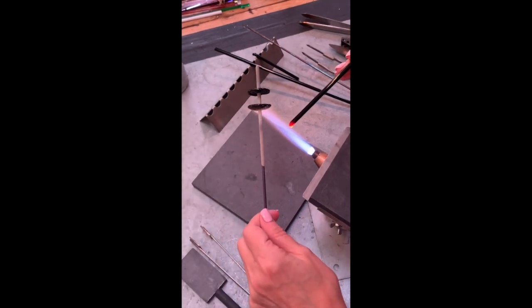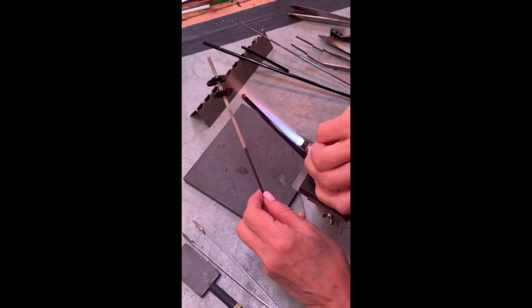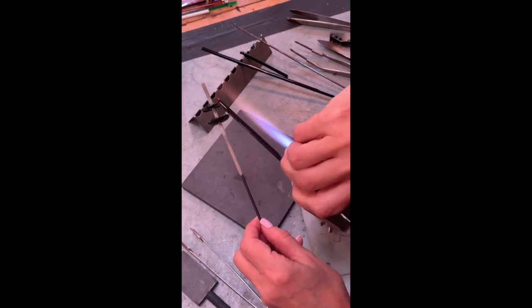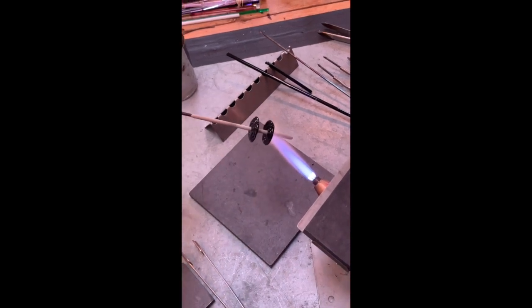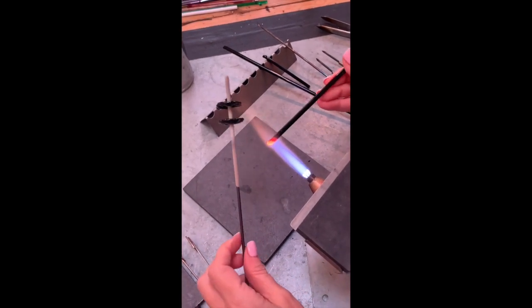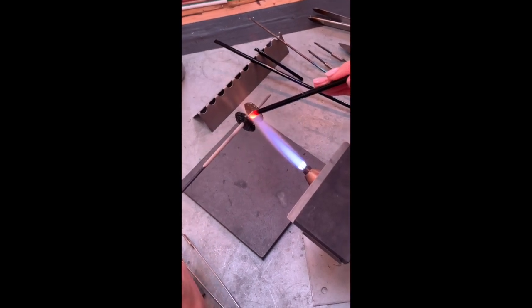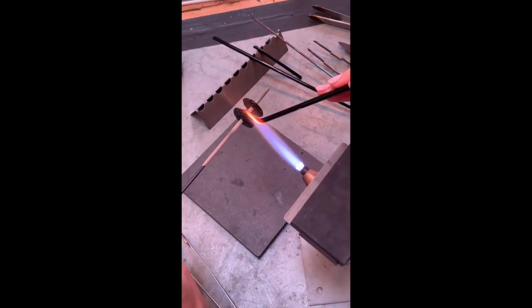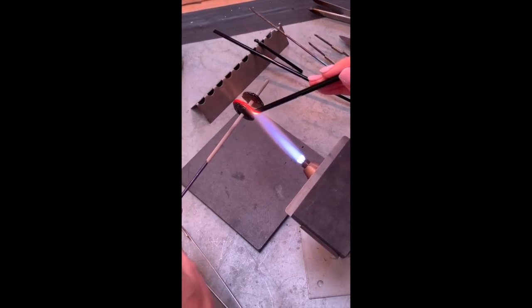So I continue to remember to heat the faces of the discs. The flame is going up, hitting this disc, and then the inside of that one. And I turn it, and then I can do it the other way. So now the face on the other side is getting warm. And at this point, where the discs are as high as I intend to make them, I'm going to start wrapping my discs just slightly to the inside of the previous disc.